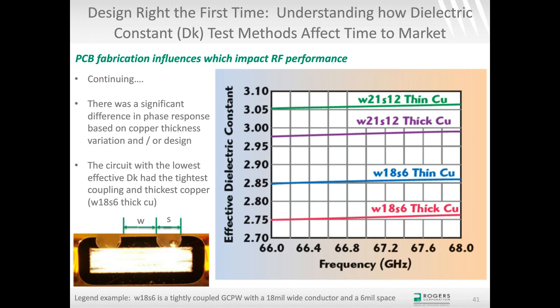Now, on the opposite end of this is the green curve at the top with the highest effective dielectric constant, and that is the circuit that is loosely coupled, a space of 12 mils, and thinner copper. So it would appear that loosely coupled with thin copper is not using the air as effectively, so it's got a higher effective dielectric constant. Now, what's interesting is, remember, this is the same sheet of material just cut in half and had circuits made. And on the same sheet of material, I'm seeing a difference of 0.3 in effective dielectric constant. That's a pretty big difference.